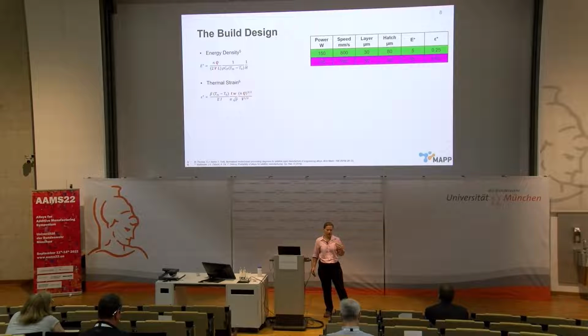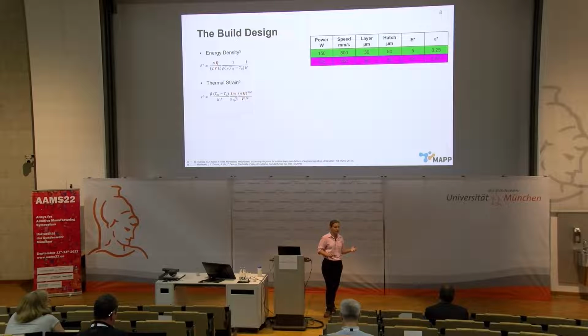So this thermal strain calculation is a comparator. It's not calibrated to an actual value of strain, but it's a way of tuning or looking at, if I build with this set of parameters, how much strain am I putting in? It doesn't necessarily look at, is that on the component scale or the melt pool scale. It's a sort of global parameter. And in this instance, T is a characteristic time, and W is the length of the melt pool.